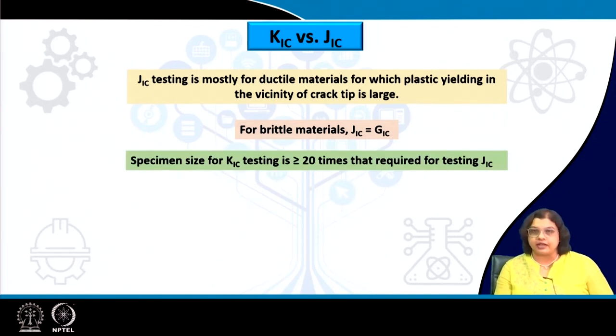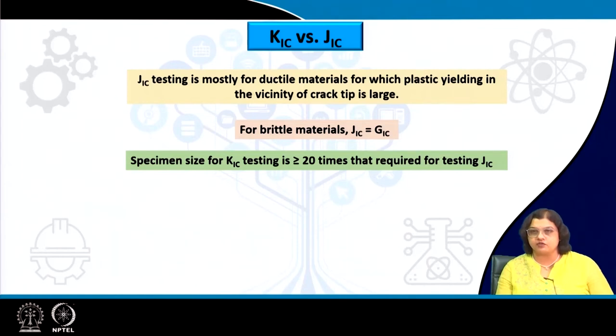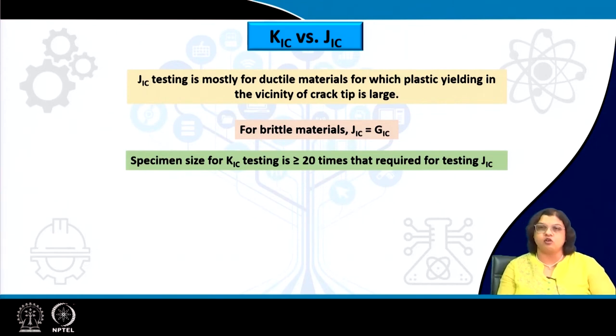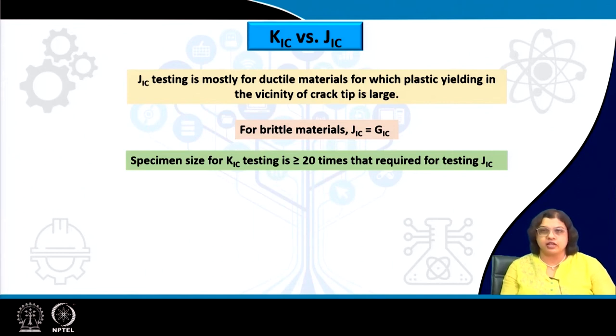The most significant difference is that plane stress fracture toughness applies for thinner specimens, and as the specimen gets thicker the fracture toughness decreases until it reaches a constant lowest value — the plane strain fracture toughness. There is certainly a difference in specimen size required for plane strain versus plane stress fracture toughness testing, and although both can use a SENB or CT specimen, the thickness can be different, and all other parameters are related to thickness.